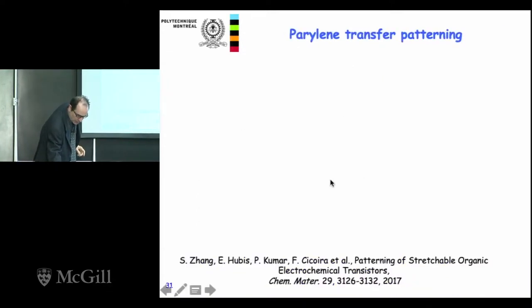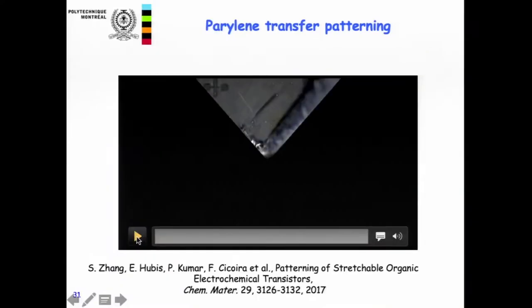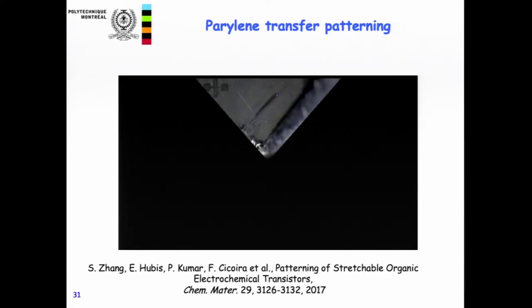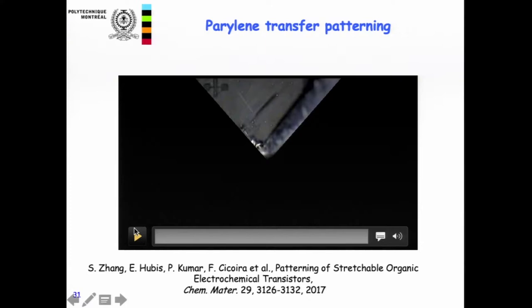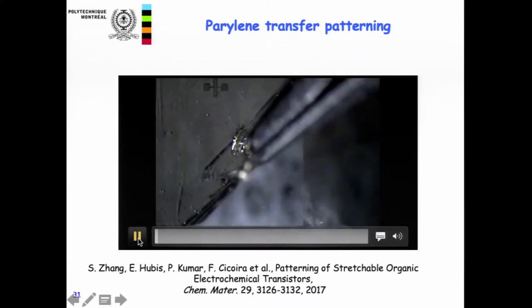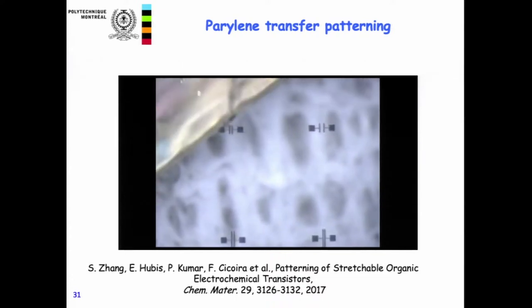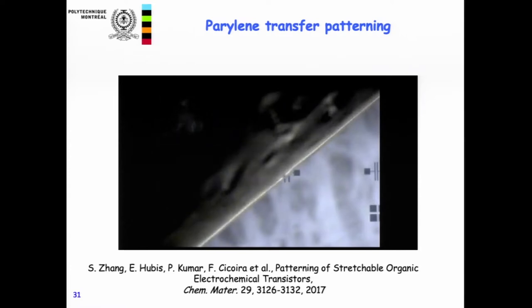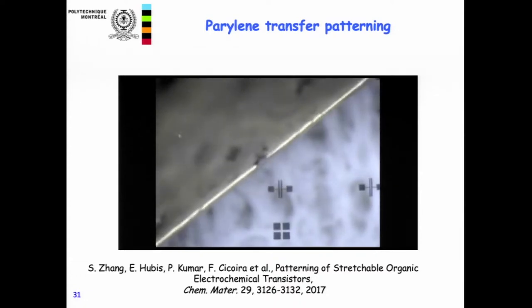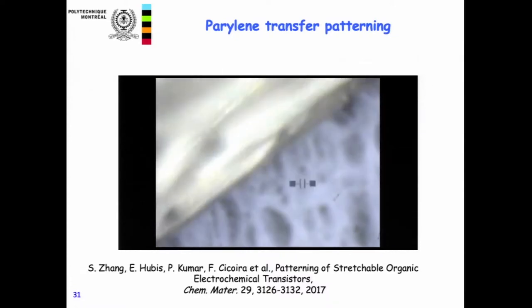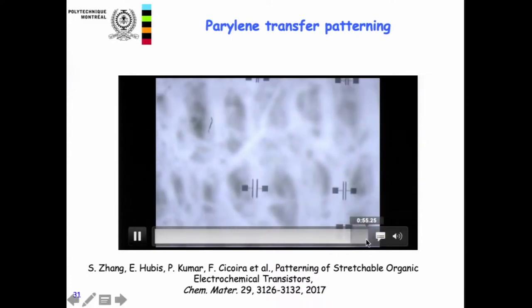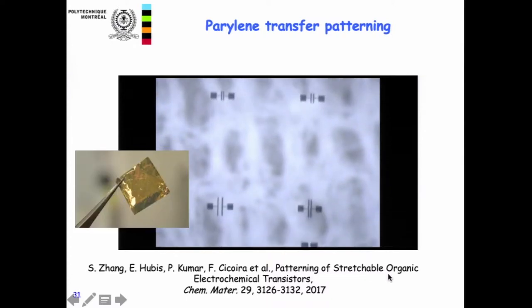Actually, I have a video about this, and you can have an idea of what happens. So this is our PDMS covered with a parylene mask after the deposition of gold, and now we just remove the parylene at the end of the process. That's the parylene that we remove. And you see that removing the mask leaves the patterned substrate. So these are gold contacts, and you see that actually there is no failure in the process. All of them are as expected. So this means that the process works very well. OK, so the video lasts for some time because I wanted to show that there are no failures, but actually I can probably accelerate it. And what is nice is that at the end of the process, you can even recover the mask and use it again for another substrate.